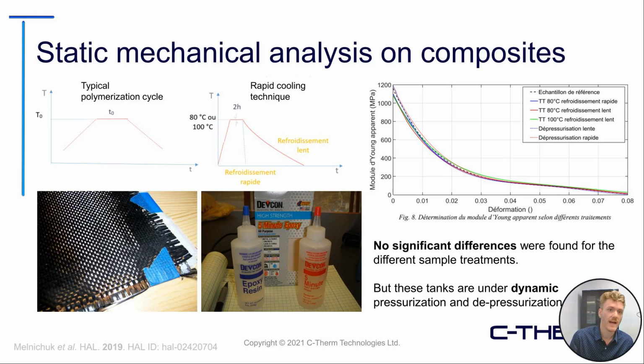So the researchers looked at particularly the composite material itself. They looked at creating these carbon fiber and reinforced epoxy resin materials. And they wanted to look at typically what would be done and a methodology to increase its strength. One methodology that was suggested in literature was a rapid cooling technique, where they rapidly cool the polymer, the epoxy resins, after curing for 2 hours. Typically, the typical polymerization is a slow and steady rise of about a degree per minute, whereas this rapid cooling consisted of up to 20 degrees per minute cooling of the material itself.